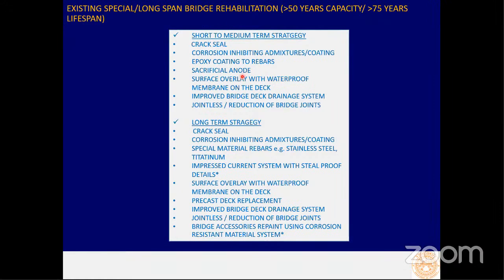For this one, we're going to incorporate short to medium term strategy and long-term strategies. For the short to medium term strategy, of course, we need to seal the crack. We do use the corrosion inhibiting admixtures coating. We need to do some epoxy coating to the rebar to repair the reinforcement recovery. And for the short term, we can install the sacrificial anode as well. And we install the waterproof membrane to the deck and we improve the drainage system. And we change the bridge to a continuous bridge and reduce some bridge joints. That is the short to medium term strategies of this kind of special bridge.